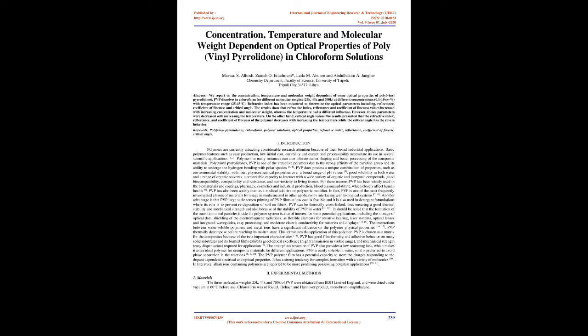to 45 degrees Celsius. Refractive index has been measured to determine the optical parameters including reflectance, coefficient of finesse and critical angle. The results show that refractive index, reflectance, and coefficient of finesse values increased with increasing concentration and molecular weight, whereas the temperature had a different influence. However, these parameters decreased with increasing temperature.